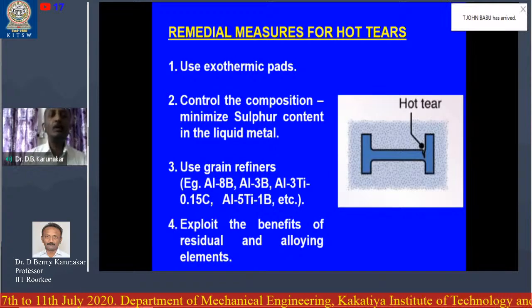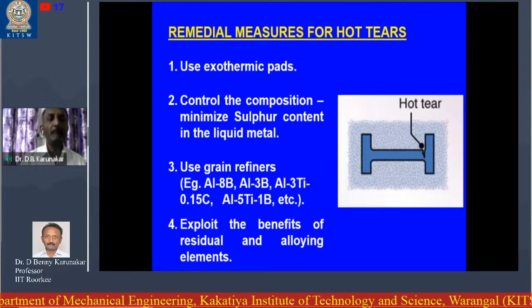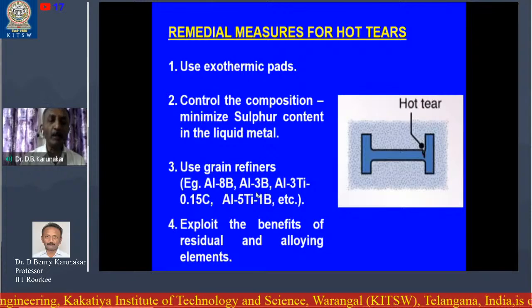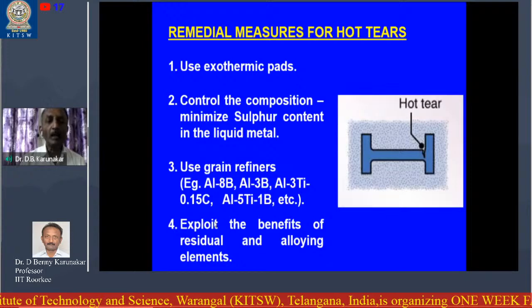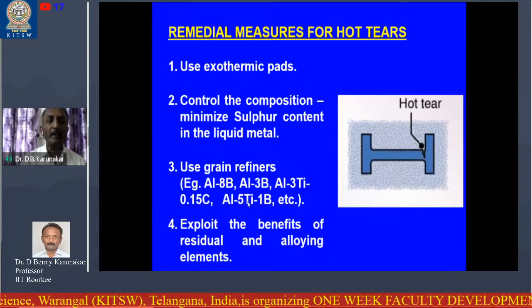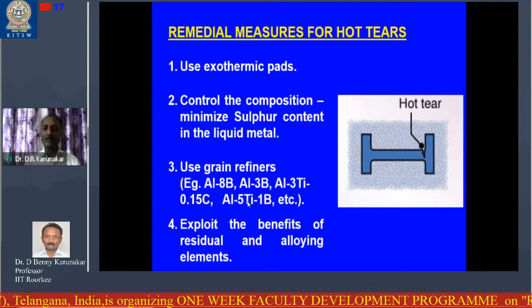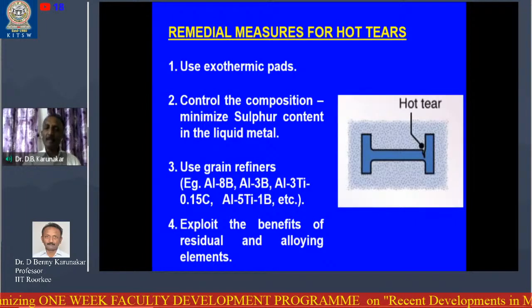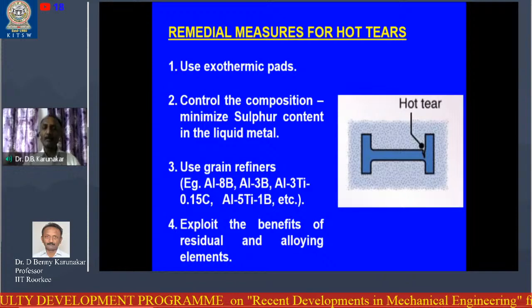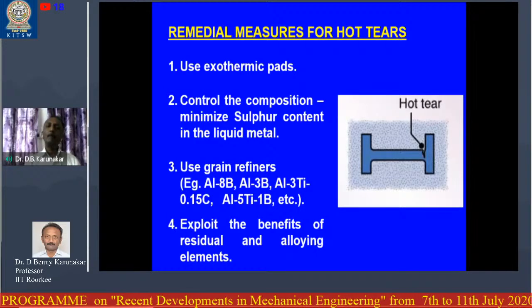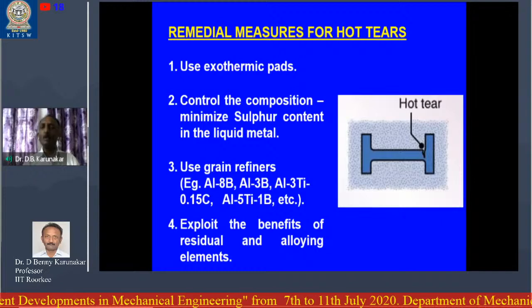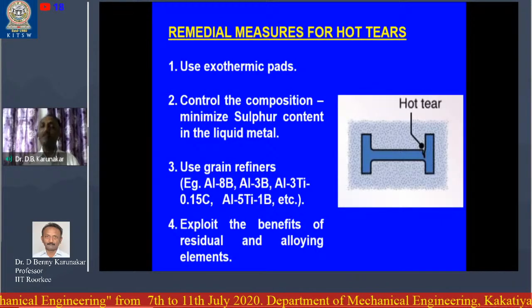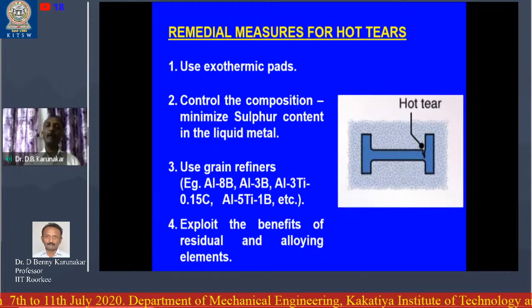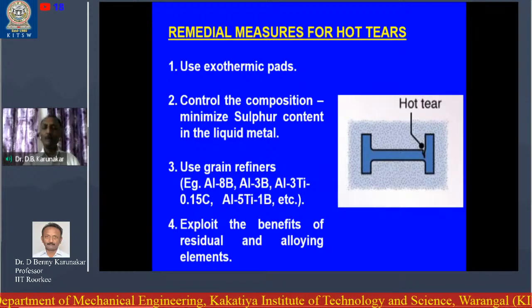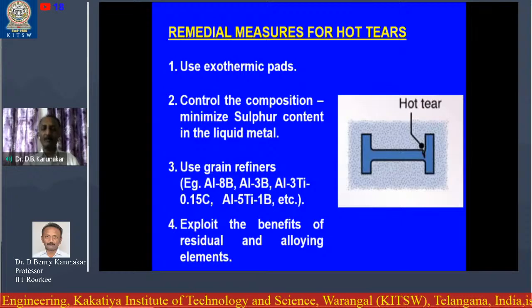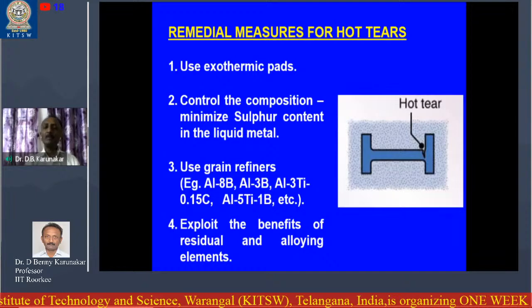Next, use grain refiners. We have grain refiners available in the market like aluminum 8 boron, aluminum 3 boron, aluminum 3 titanium, and aluminum 5 titanium 1 boron. These can be added to the liquid metal while it is still in the furnace, in extremely small amounts, maybe 1%, or in the worst case 2%. When you add these grain refiners, the coarse grains get refined into finer grains, and these finer grains help prevent hot tearing.